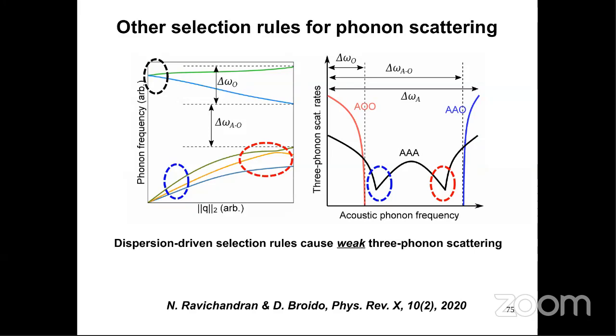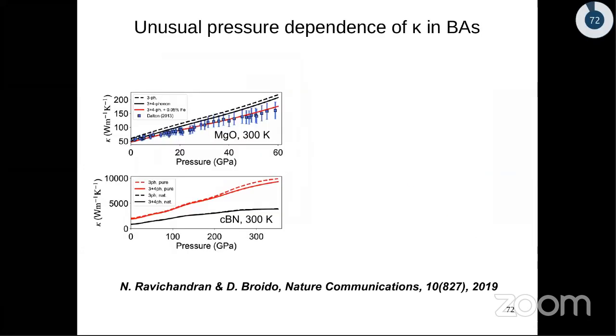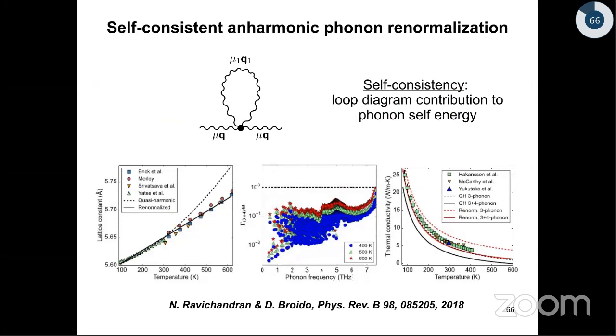Okay. So the lowest order scattering is weak because of some features in the dispersion and joint density of states. And 4-phonon scattering, just because of sheer combinatorics, does not get affected by the features of the dispersion. Yeah. So whenever you have, for example, a large mass ratio, you have a large acoustic-optic gap that basically removes one channel, AAO, that is 2 acoustic and 1 optic channel, and that exposes other features in the dispersion. So eventually you get very weak 3-phonon scattering rates, and then 4-phonon scattering becomes comparable. So it's mostly a phase space effect then. In strongly bonded materials, in the case of sodium chloride that I showed at the end, it's a combination of both. It's both strongly anharmonic, and there is some phase space effect. Okay, thank you.